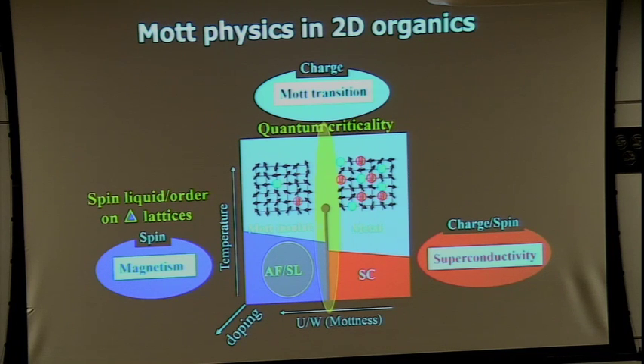Such a gap and high-Tc cuprates is under strong debate, but in this case there are no competing orders, which is different from the high-Tc cuprates. Even without competing orders, the gap appears up to twice of TC, so this is ascribable to preformed Cooper pairs.